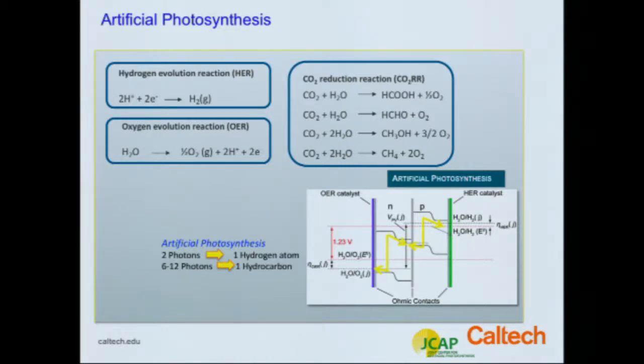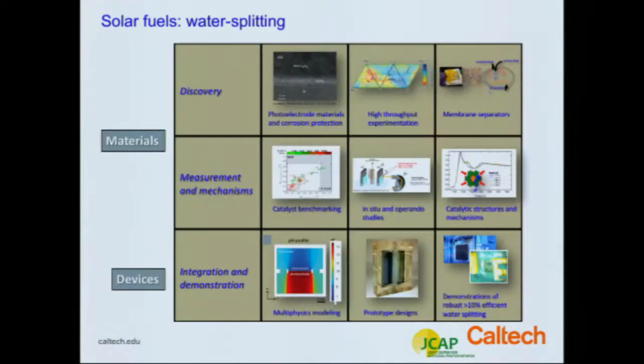So the first fuel we can make is hydrogen, just by splitting water. We use a water electrolyte. If we now add CO2 into this electrolyte, or into another medium up to the solubility limit of CO2 in that medium, we can generate other reduced products of CO2, including formate, alcohols, methane, and other alkanes.